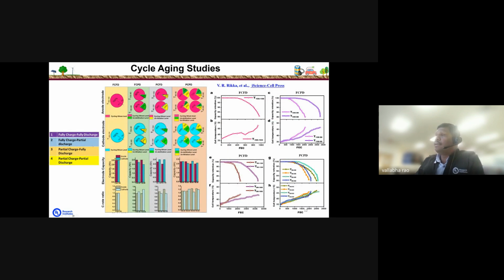Based on that, we have defined 9 test conditions. Here we can see each one. For example, the first condition is full charge, full discharge: 100% charge and then 100% discharge of the anode and cathode. Whereas in full charge and partial discharge, we have incorporated 2 test conditions: 100% SOC charge with 80% discharge, and 100% charge with 90% discharge. In the case of partial charge, full discharge, and partial charge, partial discharge, we have different test conditions.